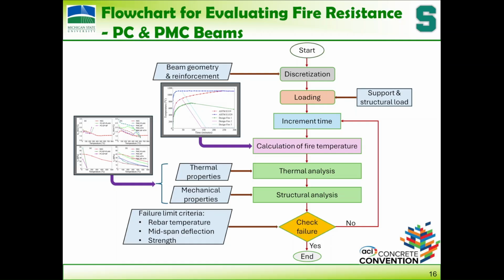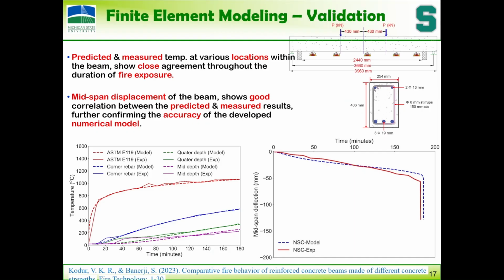Once you get the temperature rise in the structure, you can determine how much load carrying capacity it has at 5 minutes, 10 minutes, 20 minutes, 1 hour, 2 hours. You can keep going, repeating this. It's a time step analysis, right? Till the failure happens. Then we validated it, not against polymer concrete beams at this stage. I was talking to Mike there about fabricating some beams for us or finding some sources. At this stage we couldn't do it, but we did validate otherwise.